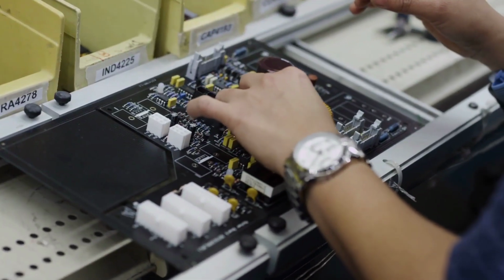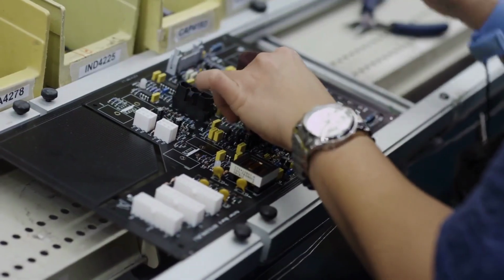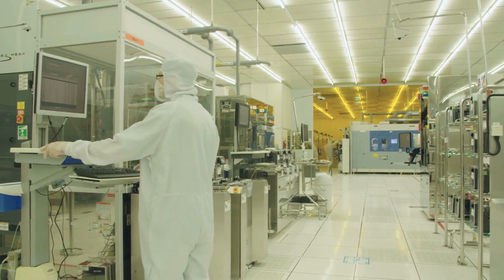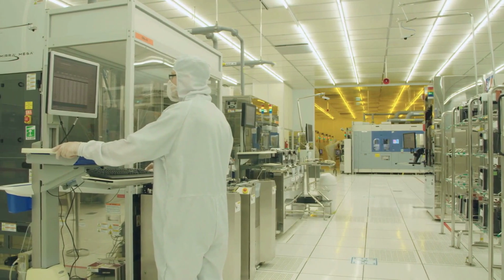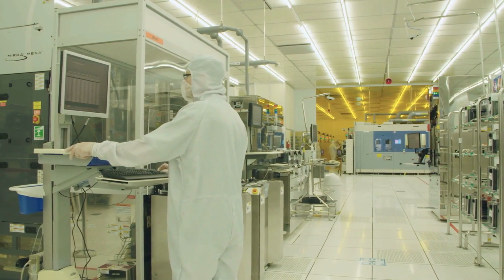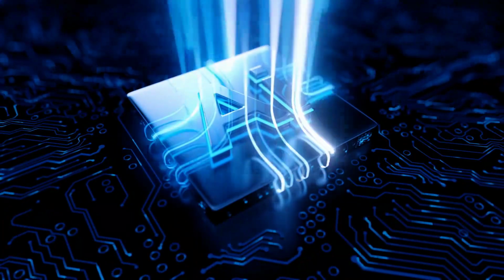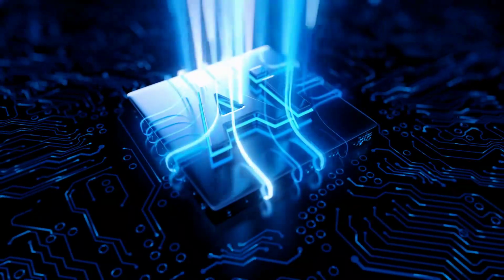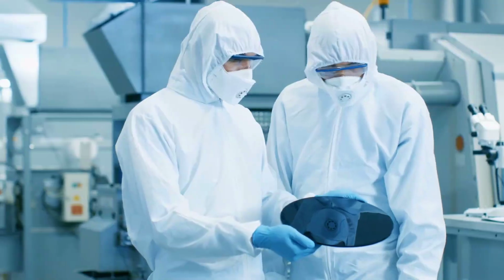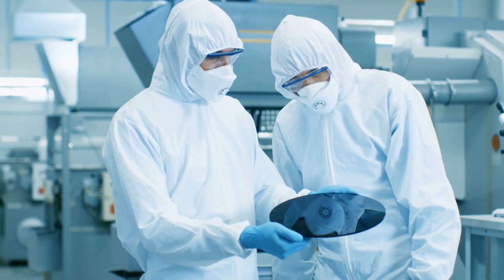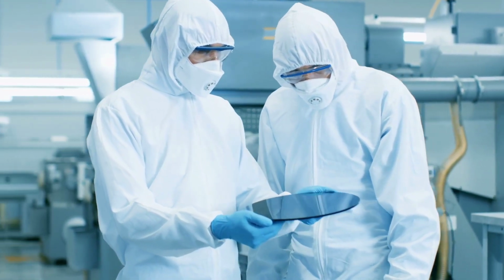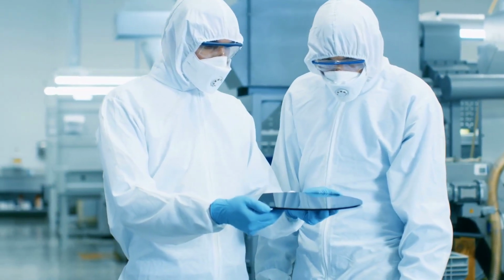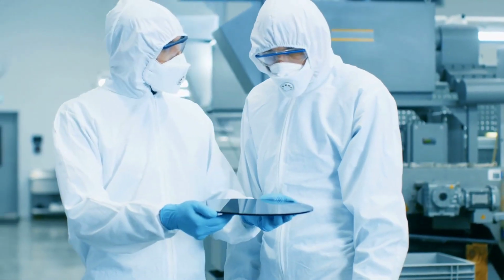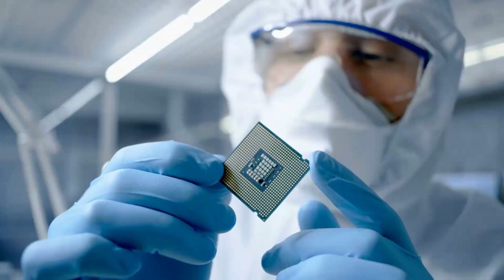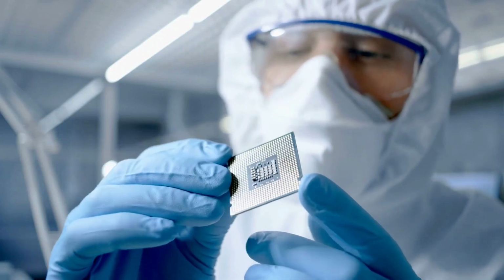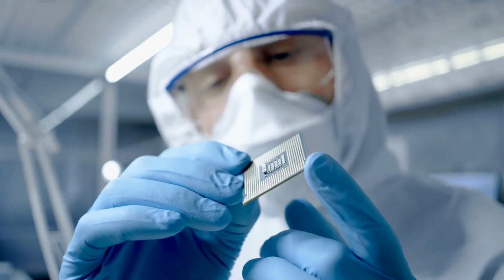Early HBM used a slow, delicate process to bond these layers. SK Hynix pioneered mass reflow molded underfill, MR-MUF, packaging technology, which improved thermal dissipation and made them the preferred partner for Nvidia's systems. In this process, all the layers are heated simultaneously, and a protective underfill material is injected into the gaps to strengthen the stack and help with heat dissipation. Samsung developed similar advanced materials to achieve the same goals.